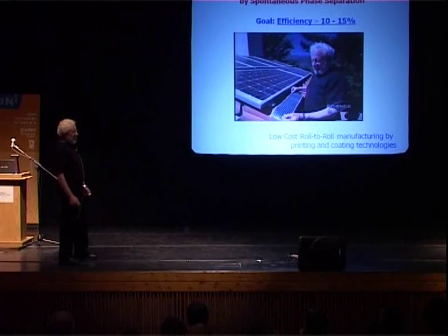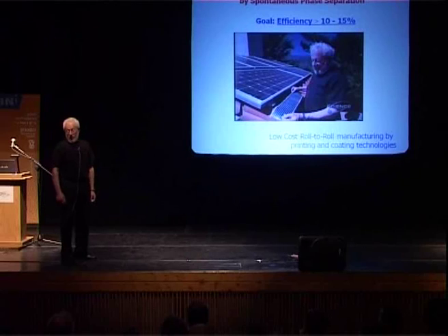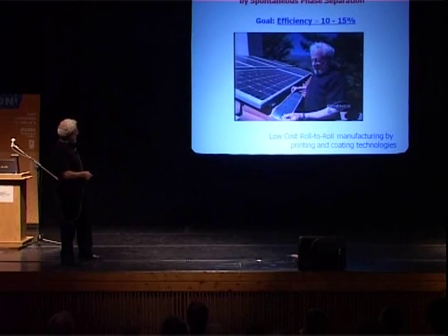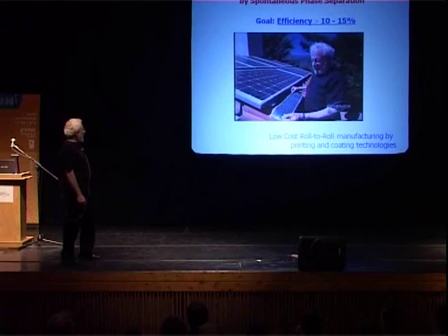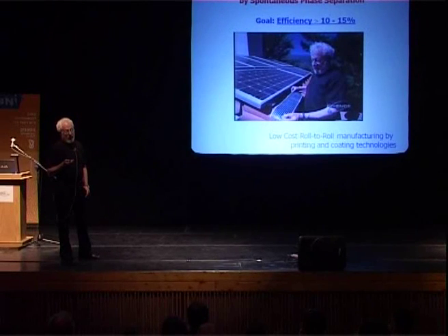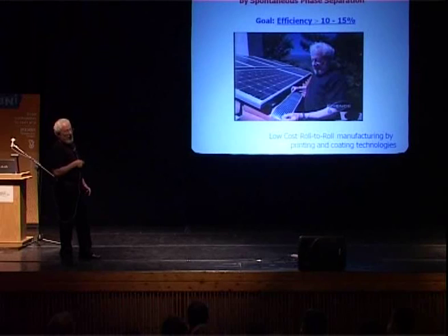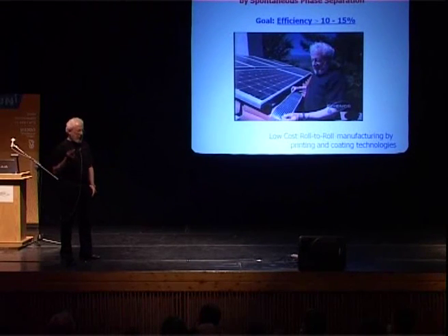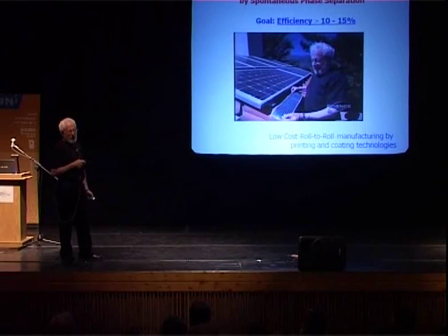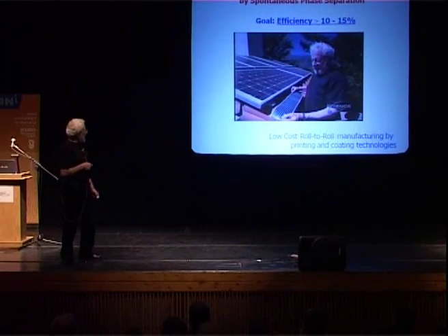Next question, obviously, is what about the lifetime? And the answer is the lifetime has to be long, or you wouldn't have a successful technology. We've demonstrated a year on the rooftop without any change in efficiency. You need barrier films. We have good barrier films. I'm pretty confident that we can get 10 years. We'll see. But that kind of work is going on, testing the lifetime, and the very first slide that I showed you was showing you that.